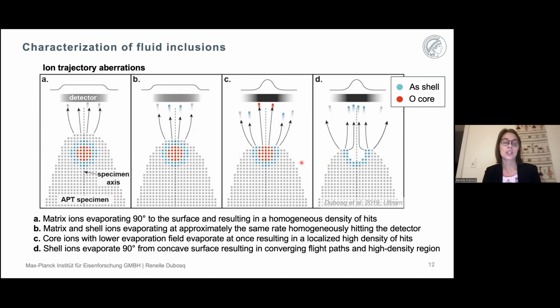On this slide, I wanted to show a schematic of what happens during the field evaporation of a sample with a fluid inclusion. In image A here, we have a pure matrix with a fluid inclusion in the center, and we start evaporating the surface of this sample. At first we have matrix ions evaporating at 90 degrees from the surface, and then they are compressed as they follow the electrostatic field. This results in a homogeneous density of hits on the detector here.